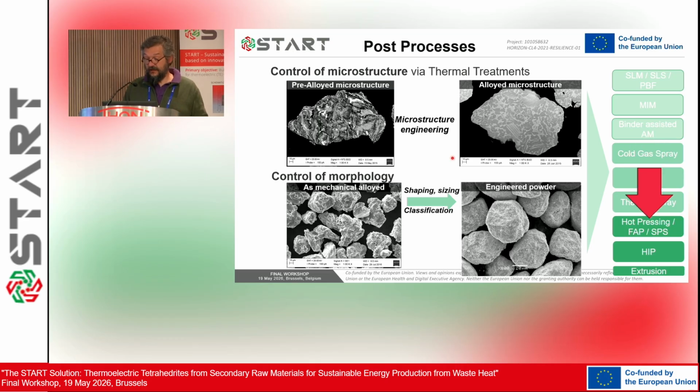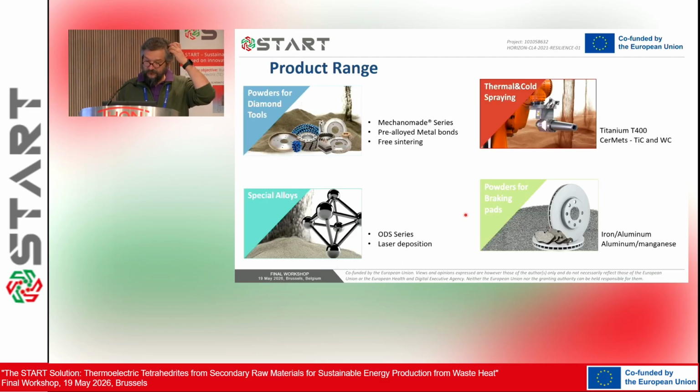As regards the project start, we are heading toward SPS. And also we are taking advantage of the thermal cycling that inevitably the material is having during SPS to avoid these thermal treatments. So our materials are going directly to the ball mill and from the ball mill to the SPS. There is a bit of morphology control, but we will see it later.